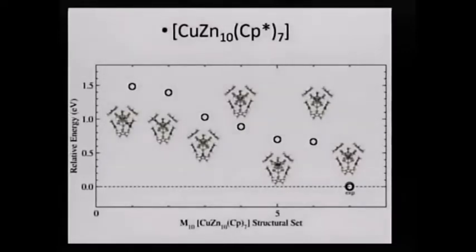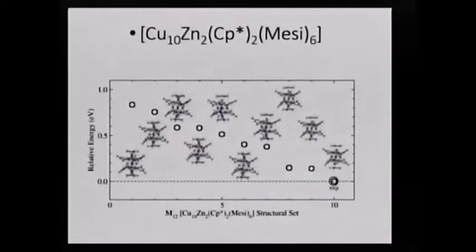However, how can you reach a lot of conformations when you have two atoms to exchange in a system like this, 12 atoms? So we performed a kind of identities classification before starting the calculation. We exchange the atoms randomly, and after this apply Euclidean metrics to provide the identities.